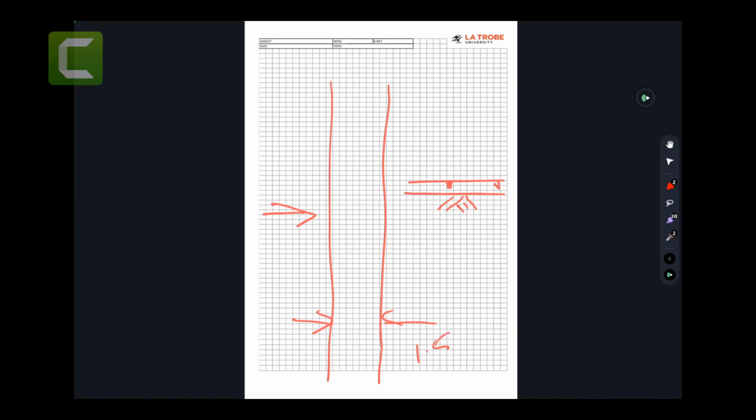So with a 1.5 meter wide footpath, pouring it at a long length, you're going to have many cracks in it, right? So they say every 1 meter or so, we're going to make a saw cut, and the saw cut will absorb those cracks. We're still having shrinkage. We cannot avoid shrinkage, but we're making saw cuts so we absorb the cracks there, and you have panels as nice as possible without those ugly cracks.